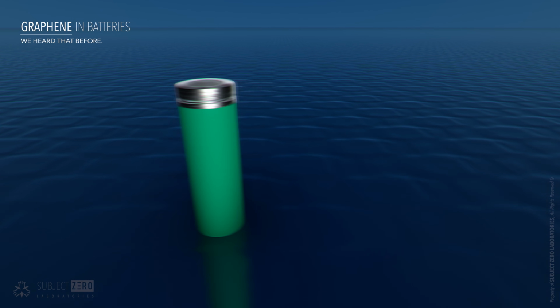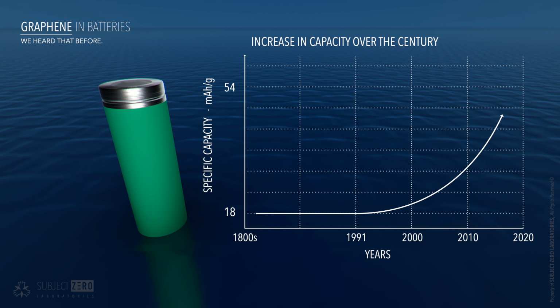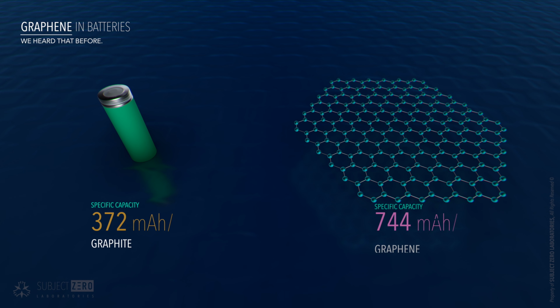As we all know, conventional lithium-ion batteries have increased their specific capacity over the years, but there is still much more to go since they are, to date, at only a fraction of their theoretical capacity. Graphene has a theoretical capacity of 744 milliamp hour per gram, with an outstanding electronic mobility at 10,000 cm² per volt-second and extremely high lithium diffusivity at 10^-7 to 10^-6 cm² per second. It holds great promise as an anode material for high-energy power lithium-ion batteries.